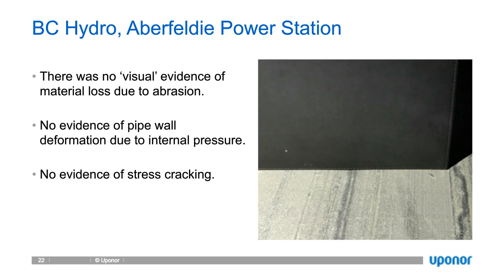This slide indicates two profiles along a straight edge, and you can see that there's no evidence of pipe wall deformation due to the continuous 20 psi internal pressure within the pipe. It's still a straight surface of the pipe, and there's no evidence of any ductile deformation in the middle of the profile wall, and no evidence of any crack formation near the ribs.